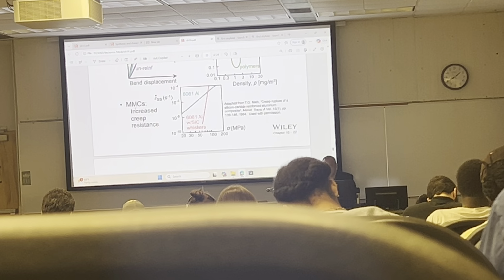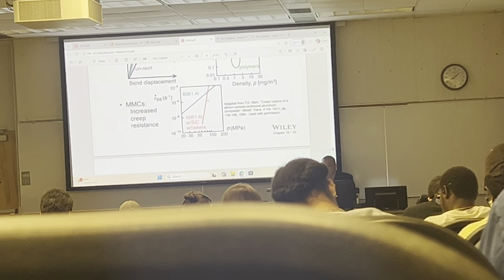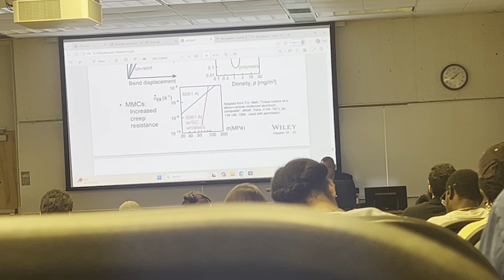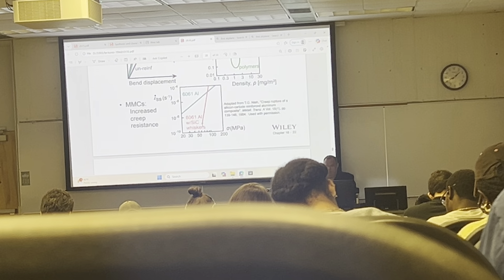Metal matrix composites. This is 6061 aluminum. This is 6061 aluminum with silicon carbide whiskers. You can see that this is in terms of the strain rate versus the stress. You get higher slope for the curve.